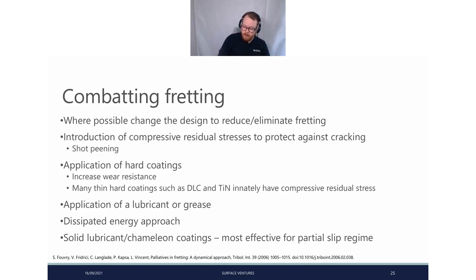So for these, typically this is in this up to micron scale regime where mechanical properties are going to determine your fretting response. A higher H over E ratio is better for this, but you don't want to go to a full, okay, well, let's remove the hydrogenation from this and we'll go to tetrahedral amorphous carbon or amorphous carbon. That is going to give you a very poor response because the friction is very high with that. So you're going to get a lot of energy expended into the fretting contact.